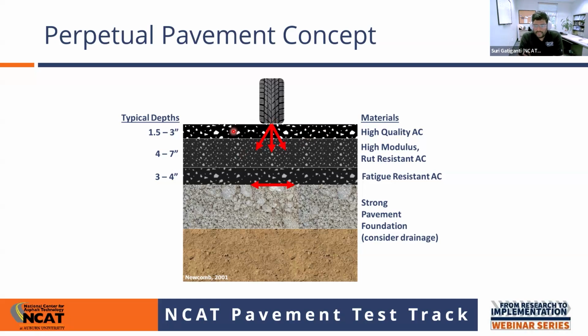And the original concept was proposed in the United Kingdom, and then it was adopted by California, by Dr. Carl Monismith's team for the I-710 project, and then adopted for one of the projects in Denver. The whole philosophy of all these initial perpetual pavement projects, as Travis said, is to have your surface layer as a high quality rut resistant mix, and have your intermediate asphalt concrete layer a high modulus, high rut resistant asphalt concrete mix, and have a rich bottom layer which can resist the fatigue cracking, and build all these three different high quality materials on top of a strong foundation. So that way, you're basically not allowing much stress to go to the subgrade, and you're protecting the subgrade that way.